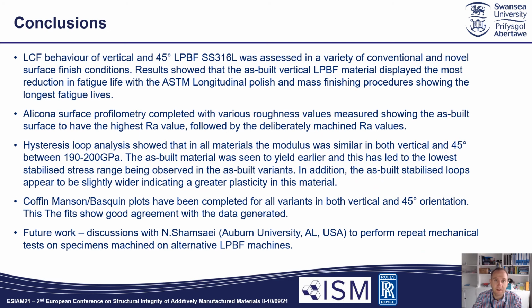So to conclude, the LCF behaviour of vertical and 45-degree orientated LPBF stainless steel 316L was assessed in a variety of conventional and novel surface finish conditions. Results showed that the as-built vertical LPBF material displayed the greatest reduction in fatigue life, with the ASTM longitudinal polish and the mass finishing procedures showing the longest fatigue lives. Alicona surface profilometry was completed with various roughness values measured, showing the as-built surface to offer the worst finish, followed by the deliberate Ra values.